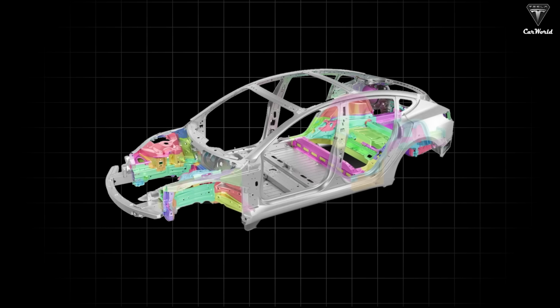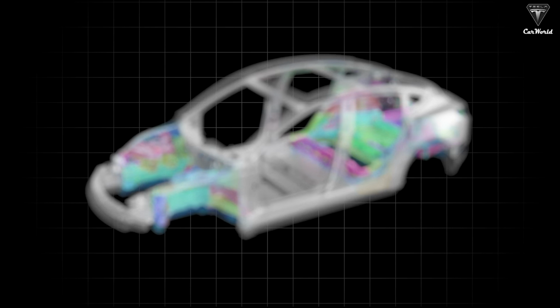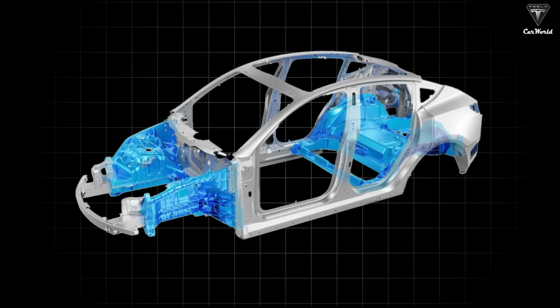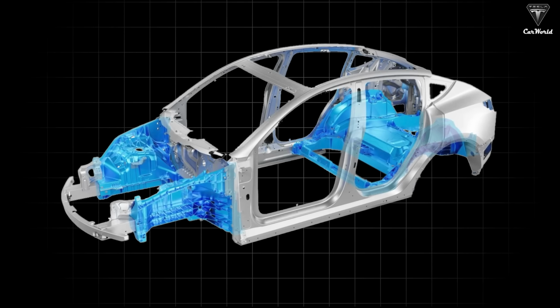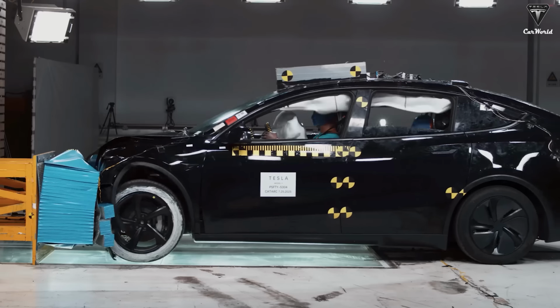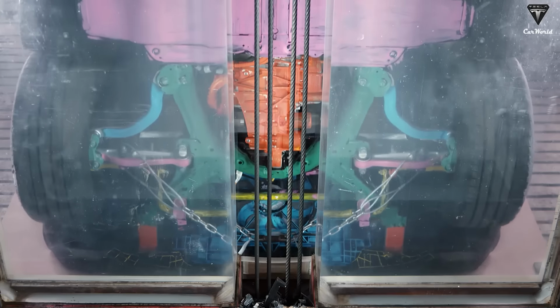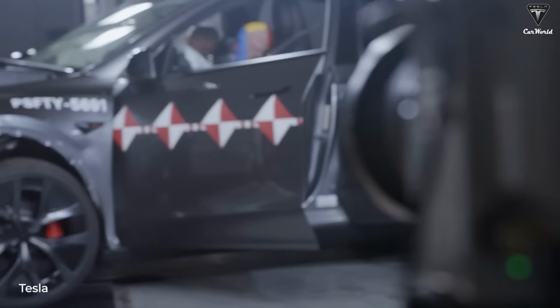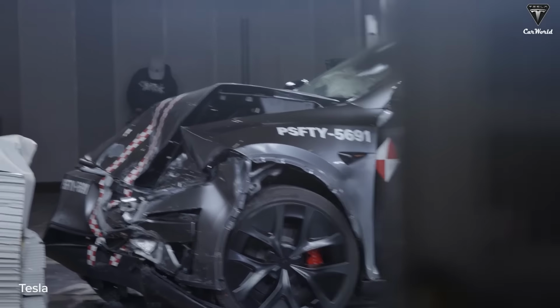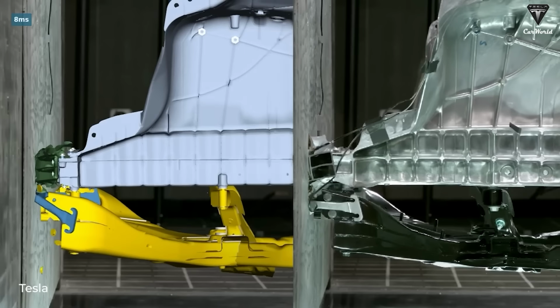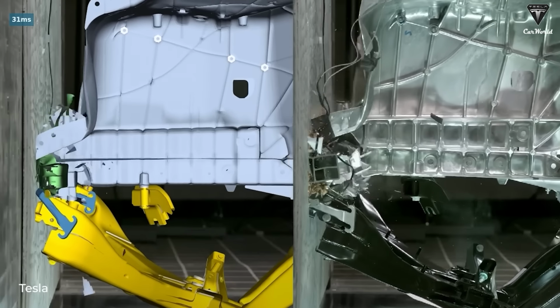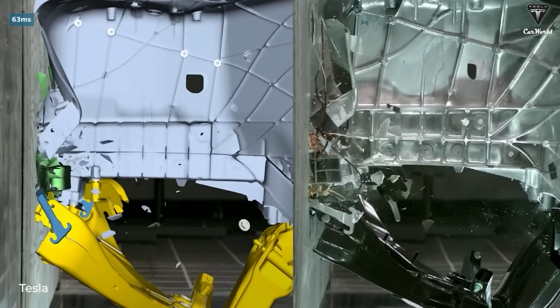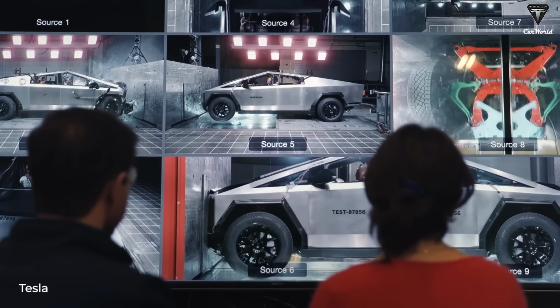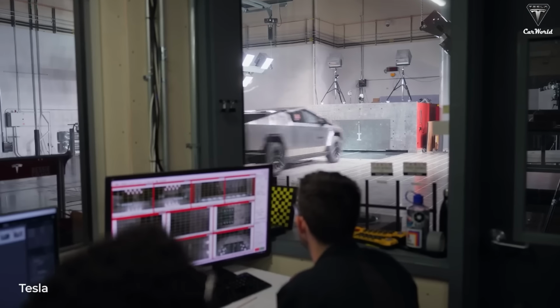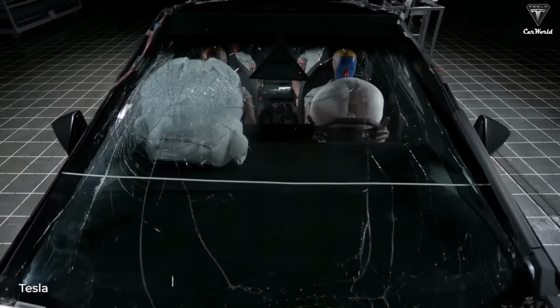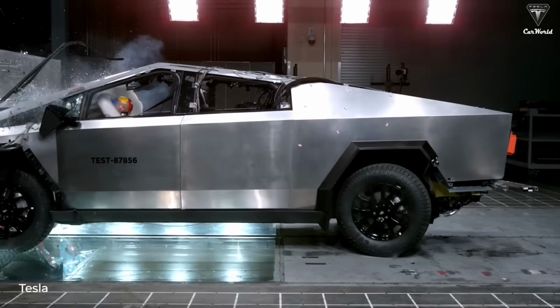But there's an important misconception here. People often assume that if a structural assembly consists of 70 welded components, you can simply replace whichever individual piece gets damaged. But if those 70 components are consolidated into one massive aluminum casting, even a crack in one small area could mean replacing the entire casting. In theory, that sounds perfectly reasonable. But in reality, repairability depends on how the manufacturer designs the vehicle's crash absorption zones and the repair procedures that go along with them. It's not simply a matter of how many individual components make up the structure.